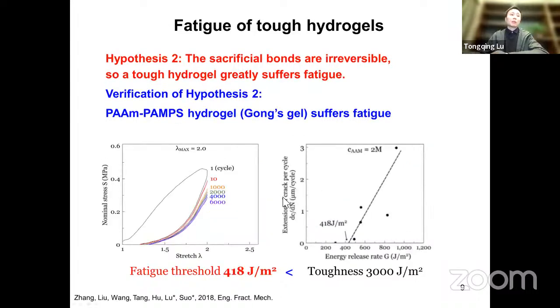Yeah. So in our group, we first studied the fatigue of Gong's gel. Gong's gel is the first generation of the tough hydrogel. It's more famous actually. So the hypothesis is the same, because in these double network hydrogels, there are also sacrificial bonds. In the stress strain curve, we can see the first cycle has a large hysteresis, so it greatly suffers fatigue. And we also measured the fatigue threshold of Gong's gel. We find that the fatigue threshold is about 400. So the fatigue threshold is smaller than its toughness, about 3,000, but the number itself is still very big.